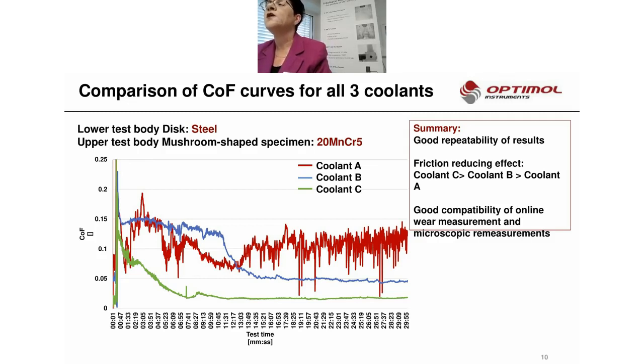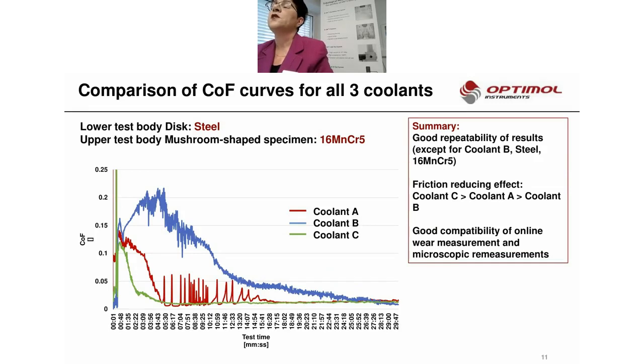And then the other example is for steel and 16 mangan chrome 5. Again, coolant C is very constant, as you see here. Coolant B is not so good, and coolant A even has a low coefficient of friction value, but the fluctuation and the stability of the friction is not as good as coolant C.